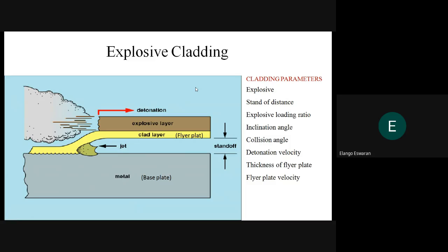And explosive cladding is associated with a number of parameters that influence the mechanical strength and the weld zone. The factors influencing the explosive cladding process are explosive standoff distance, explosive loading ratio, inclination angle, collision angle, detonation velocity, thickness of the flyer plate, and velocity. So this is the base plate and this is called the flyer plate. There are two types of explosive arrangement, that is parallel configuration and inclined configuration. In the parallel configuration, the flyer plate and the base plate are parallel to each other, but in the inclined configuration, the flyer plate makes a particular angle with the base plate. The standoff distance is the distance between the flyer plate and the base plate. The explosive loading ratio is the ratio of the mass of the explosive to the mass of the flyer plate. And inclination angle is the angle between the flyer plate and the base plate.